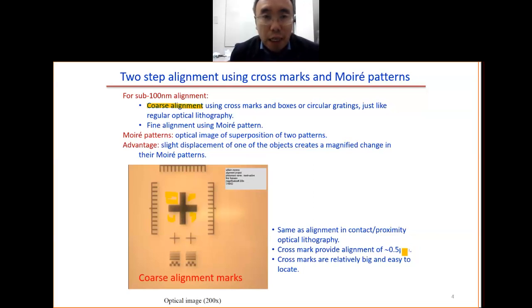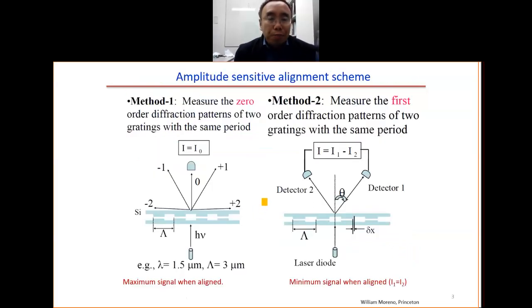So how to do that? One way is to use gratings. You put the grating on the mold, you put the grating on the wafer, they have the same period, you shine the light, you do the detection, you measure the transmitted light. In this case, we measure the zero order diffraction. So when they are aligned like this, you get the maximum signal here.